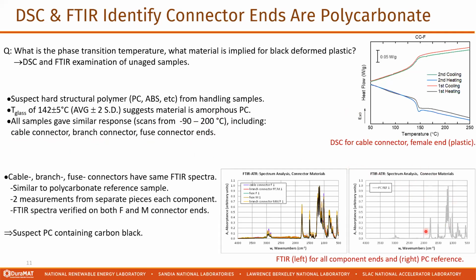I show here a reference sample of polycarbonate, and that's shown relative to samples extracted from these same components. We looked at at least two separate pieces of each of the components, and we verified both the female and male connector ends. Long story short, this looks like it's polycarbonate, probably containing carbon black to stabilize it.